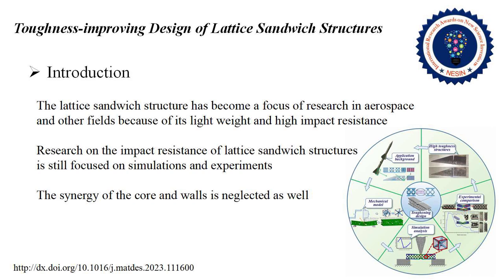Taken together, the existing studies of lattice structures mainly focus on the basic mechanical responses, energy absorption effects, and reinforcement effects of the lattice core on sandwich structures. Although scholars have explored the impact energy absorption of lattice sandwich structures to seek high toughness and impact resistant structures, these works mainly involve experiments and simulations and lack theoretical models. The synergy of the core and walls is neglected in these works as well. In our study, we coupled the BCC lattice between the walls of the sandwich structure to form a lattice sandwich structure. The toughening mechanism and design method were studied systematically.